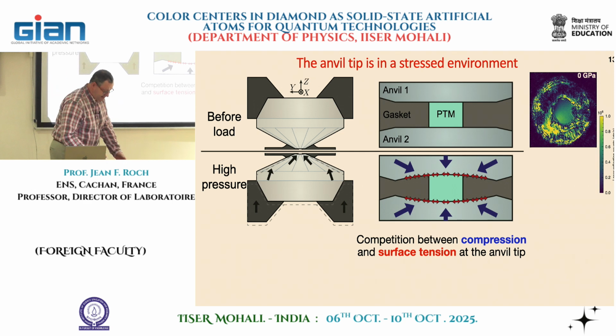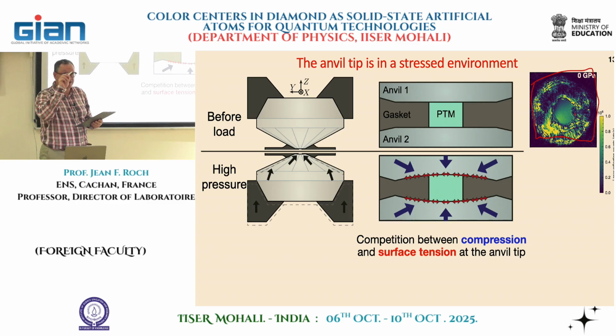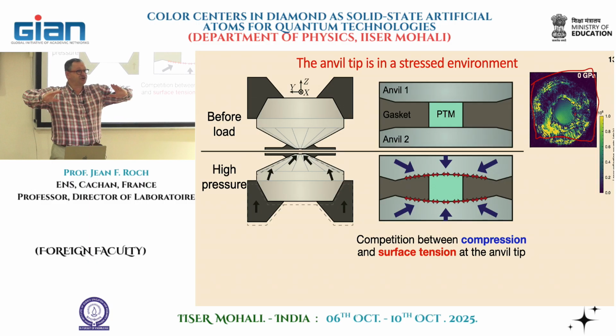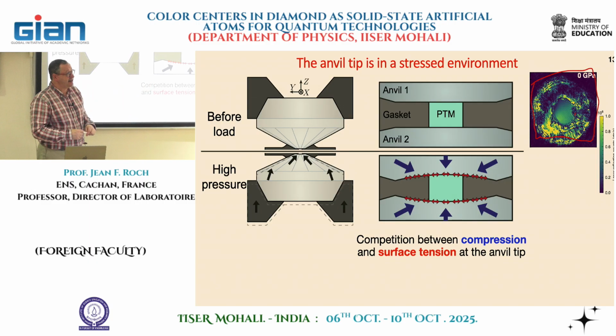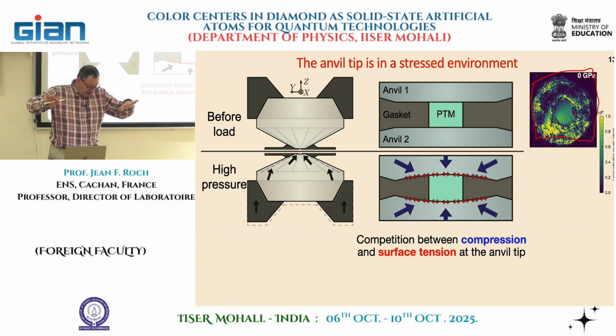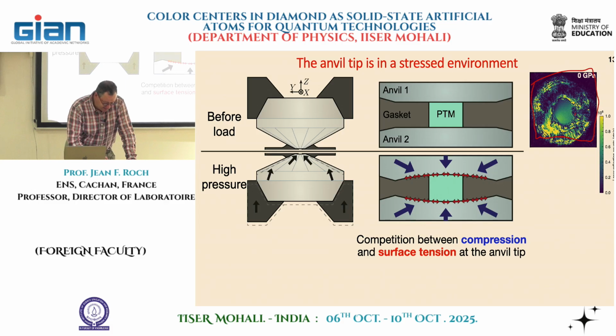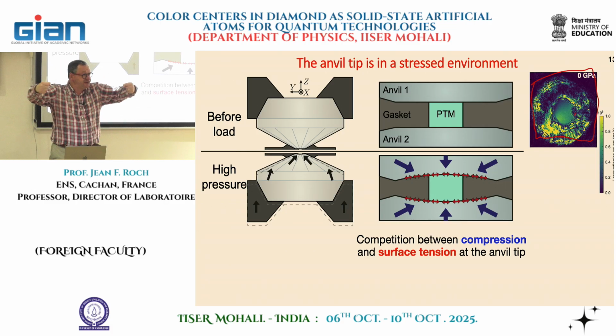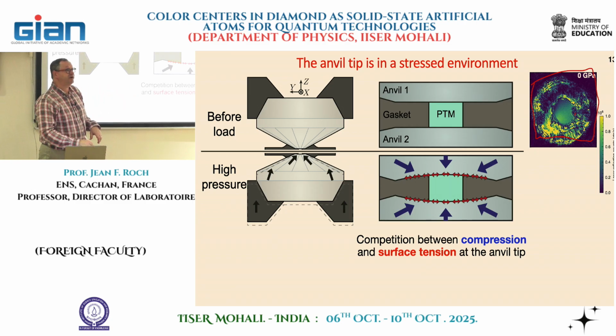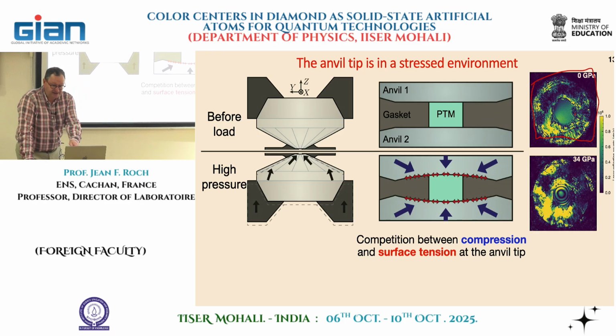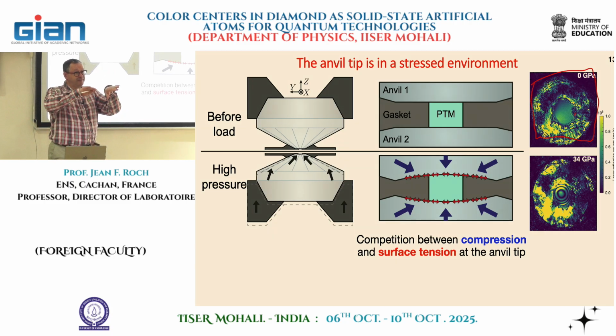This is observed, for instance, in this observation here. You see there is a uniform light when we look through the anvil. But when we apply pressure on the tip, you can imagine that there are huge forces concentrated on the tip, together with the huge forces exerted laterally by the tip. So the anvil tip now has a curvature. There's a cupping effect on the tip, due to the competition between compression on one side and surface tension on the other side, which leads to a specific shape that you can really observe. The distortion, the fringes here, tell you that you have interference, this shape of the diamond anvil.